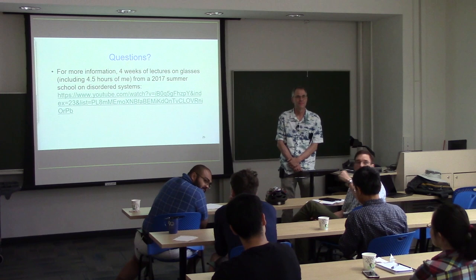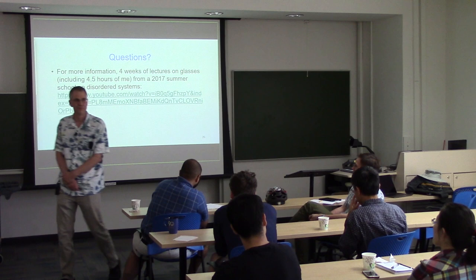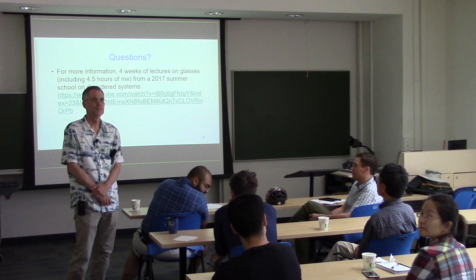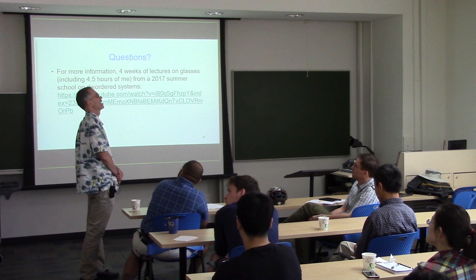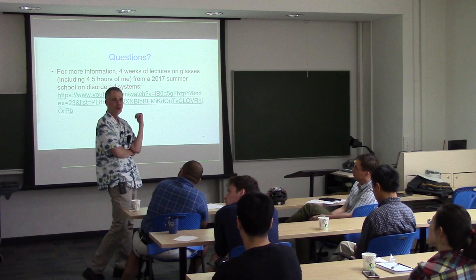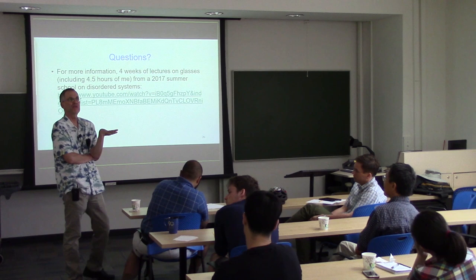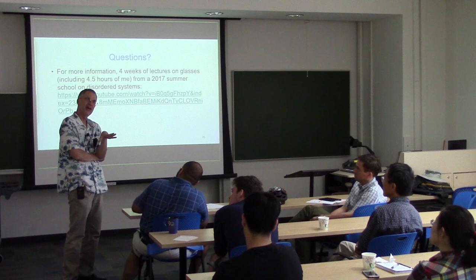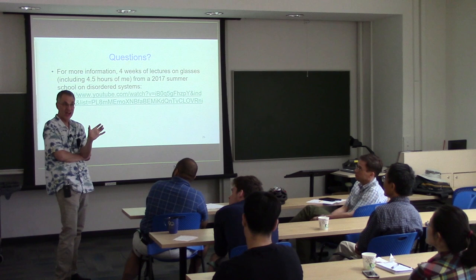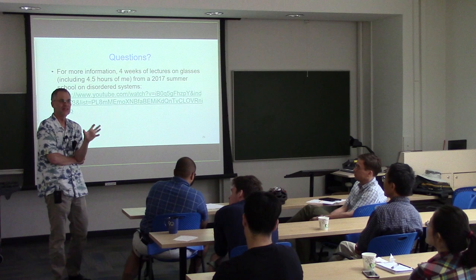You mentioned the advantage of the vapor deposited glasses being that you can get them denser and more tightly packed. How does that translate into useful properties? What's better about having these denser glasses? So the question is what useful properties would vapor deposited glasses have, or maybe better properties than a liquid cooled glass. The OLED example is one that we've thought about. Vapor deposition for many systems will produce glasses that are 1% more dense than a liquid cooled glass. But that 1% can buy you, in an isothermal experiment, a factor of 10 to the 5 in kinetic stability. So the glass packing will hang around 100,000 times longer than the liquid cooled glass.